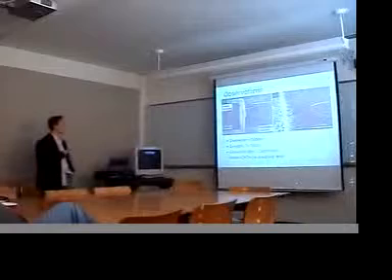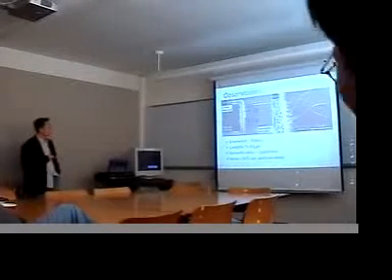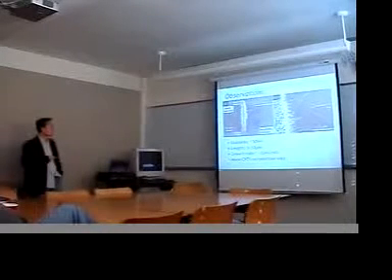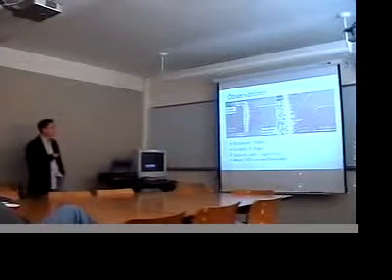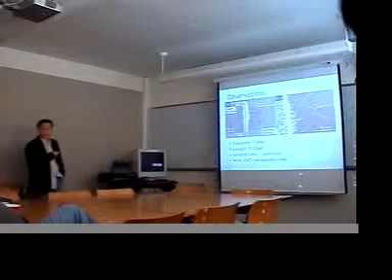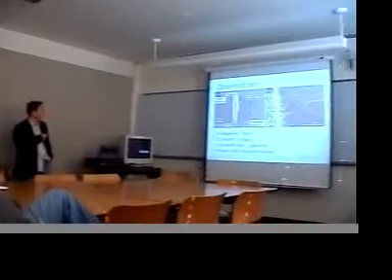So, some initial observations: the carbon nanotubes that we grow are pretty thick, around 50 nanometers in diameter, and the length varies between 5 to 10 micron. The growth rate is about 3 micron per minute. And as you can see, over here we have around 4 connections, over here 3 connections, over here 2 connections. This is another indication that the electric field plays a big part in a successful connection. We are applying a positive bias over here to heat up this side, so over here we actually have a much higher electric field compared to here.